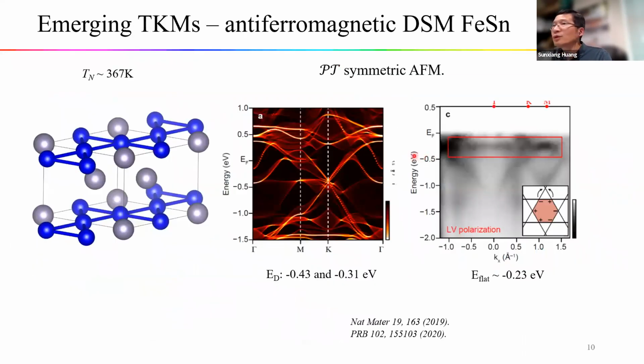So let me quickly go through the antiferromagnetic Dirac metal iron-tin. It's an antiferromagnet with a Néel temperature of about 370K, but it's a collinear antiferromagnet. So in each Kagome plane, the spins are along one direction. Between neighboring Kagome planes, the moments are aligned antiparallel. The photoemission measurement also confirms the Dirac nodes as well as the flat band in these materials. Also, another interesting feature is that this is a special antiferromagnet with PT symmetry.